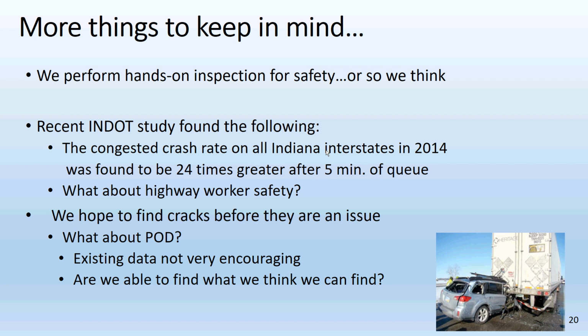In other words, we go out and we inspect, and there's several hundred folks on the call today. Well, let's say we all went out to a bridge and we inspected it, and let's just say we're looking for cracks. Does anybody really think we would all come back with the exact same answer in terms of how many cracks we found? Well, we did a little study at Purdue where we took specimens. We put them up in the air. We put real fatigue cracks in them, and we ran real inspectors, 30, through. They knew they were being tested, and we ran them through the course just trying to get a feel for what is their probability of detecting given fatigue cracks.